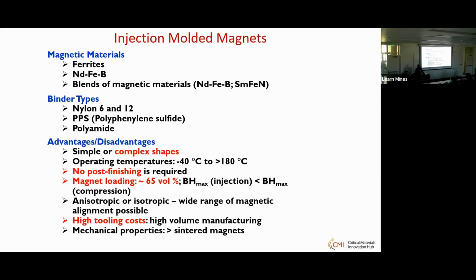A lot of car parts, the motors as well as the music system and all the things, everything is made of injection molded magnets. So nylon, polyphenylene sulfide PPS, or polyamide 6 and 12, these are standard binder types used. So you can actually make complex shapes, and the operating temperature can vary from minus 40 to 180 degrees, with no post finishing. A lot of times with injection molding, once you make it, it's a very fine surface.